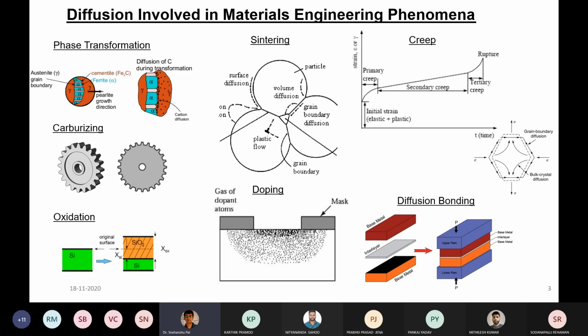or localized bonding can be formed. Now, what are the different mechanisms that are dominant with respect to the sintering process? If you look at the picture, inside the particle, volume diffusion can occur. And if it is a metallic particle, dislocation phenomena can occur inside the particle. And in the picture, there is one edge dislocation.